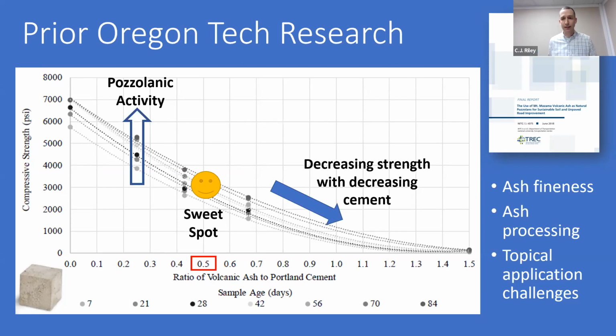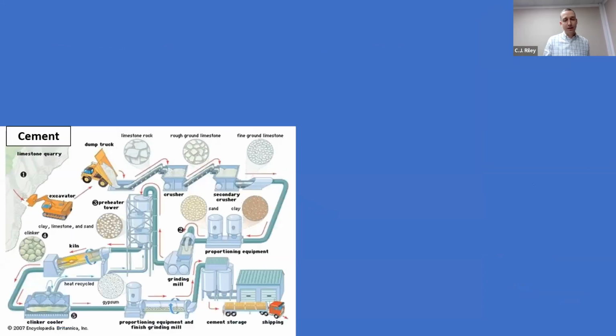Some of the other issues, though, that this study found were that the fineness of the raw ash was not as fine as necessary to characterize this as a class N pozzolan. So some grinding or processing would be necessary to use it that way. And then attempts were made to apply this as a topical treatment to some ash surfaces, and issues around clogging were identified. And so those were some of the challenges that we knew we were getting into when we started our work. I'm going to hand this back to Ashton to tell you a little bit more about materials, and then I'll come back and tell you some more about how we developed our batches.